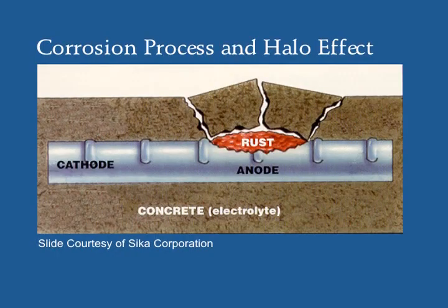After a while, the maintenance forces will come along and finally replace this deteriorated concrete. They'll replace it with chloride-free concrete in this patch, and then subsequently, this part of the system, previously the cathode, will become the anode, now having greater chloride concentrations than its adjacent steel, and now the corrosion process will be initiated at this location. Thus, you see how the halo effect occurs in the field, a continuous growing of this damage process.